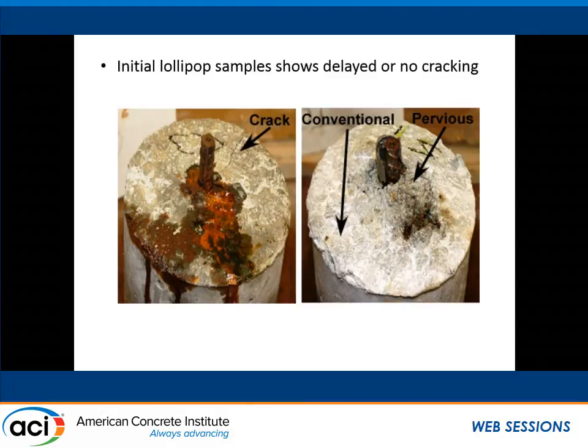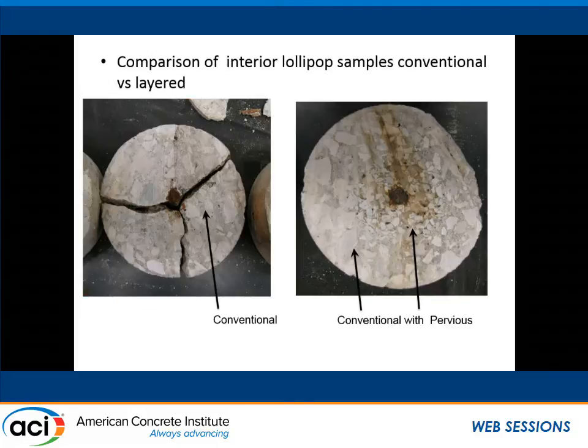So here's our conventional. You get corrosion. It splits. The corrosion product goes everywhere. Here's the pervious core. We have corrosion. We can see corrosion products kind of bubbling out the top, but we didn't split it. Then we take them and saw cut them, and here's our conventional. It definitely expanded and split. Our pervious, it definitely expanded into those pervious voids. So you say, okay, maybe that's interesting. Let's progress to the next stage.